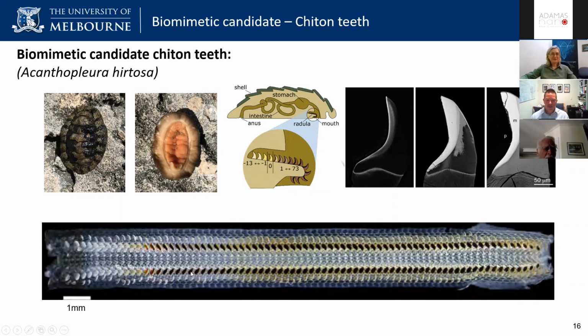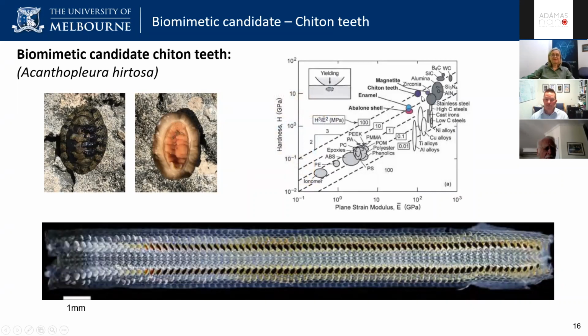And what's nice about this process is you've got a whole snapshot of how this animal is producing these teeth in one radula. So you can look from the very beginning all the way through to the very end. And as I said, in terms of the hardness of these teeth, if you put this on a plot against a lot of other materials, the teeth from this animal are harder than stainless steel. And so these animals are making their own teeth in seawater. The way that they make their teeth is they collect iron from the seawater, and they are able to assemble the iron in such a way that they can create these incredibly hard teeth that are harder than stainless steel. And they're doing it at a temperature of 15 to 17 degrees.